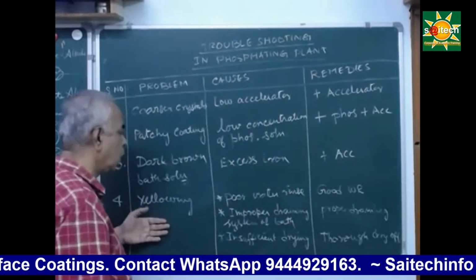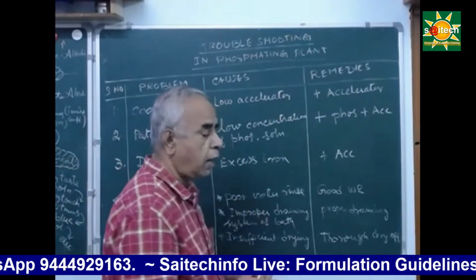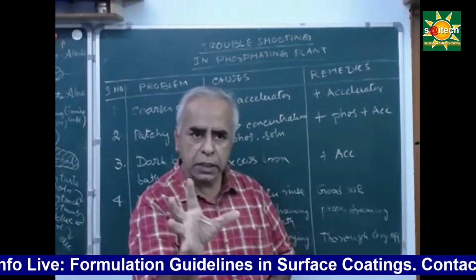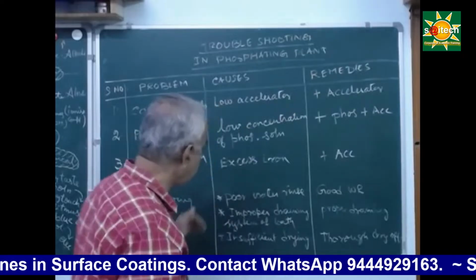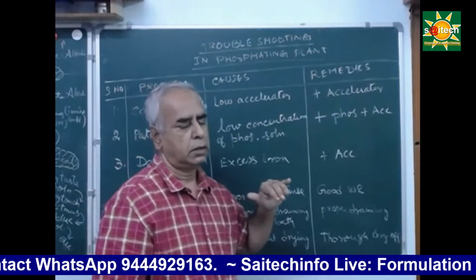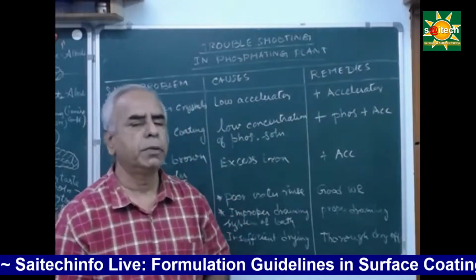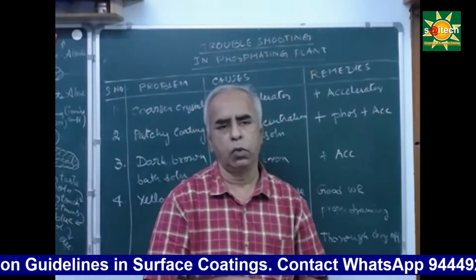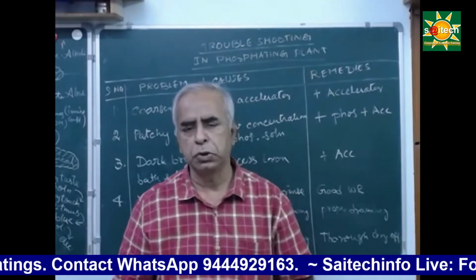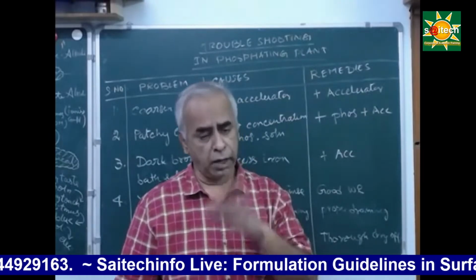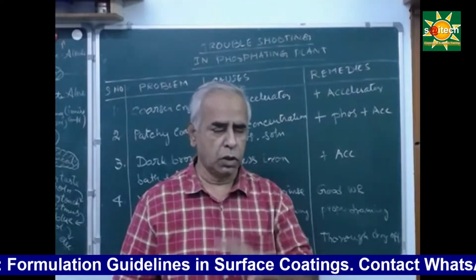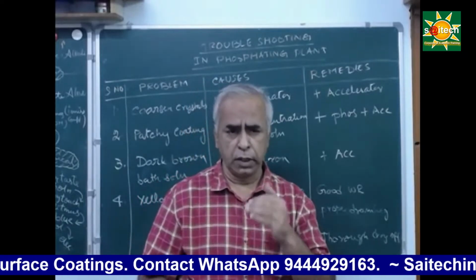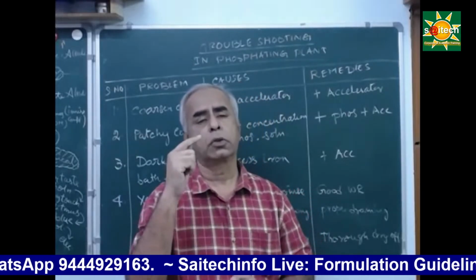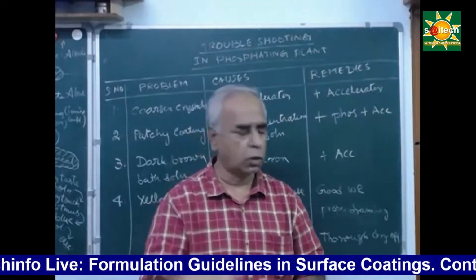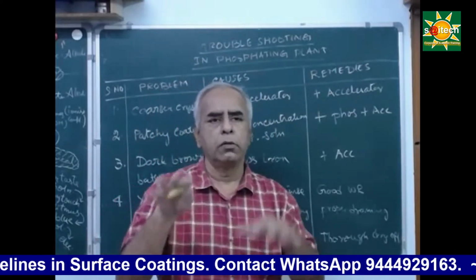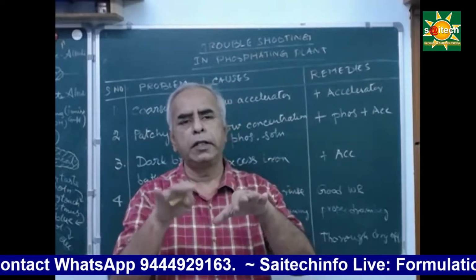Okay. Then yellowing means, after phosphating, there are some yellow patches found on the phosphate layer. So it may be due to what, a poor water rinse. They would have not properly rinsed with water. Some people simply rinse with water, they don't use DM water. In my opinion, always a phosphating solution should be made up only with DM water, and after that you have to use only DM water. You should not use normal water for rinsing. That will give you a better performance. And not only that, you should constantly replace that DM water also. And some people will have some overflowing arrangement, and they will maintain a constant flow of DM water.